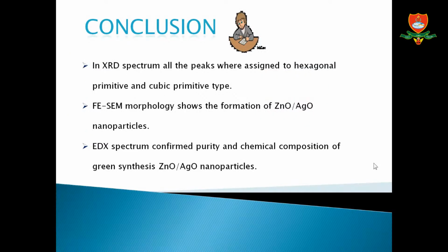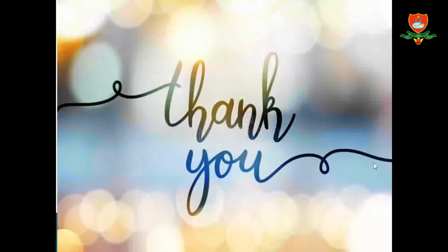Conclusion. In the XRD spectrum, all the peaks were assigned to hexagonal primitive and cubic primitive types. FESEM morphology shows the formation of zinc oxide and silver oxide nanoparticles. The EDX spectrum confirmed the purity and chemical composition of the green synthesized zinc oxide and silver oxide nanoparticles. Thank you all.